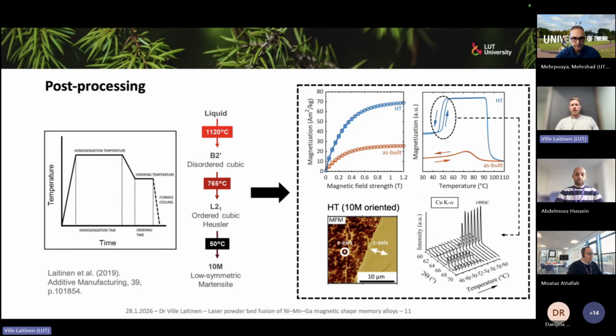At the bottom, you can see a magnetic force microscope image of a very specific orientation of a laser powder bed fusion fabricated nickel-manganese-gallium. You can see this characteristic domain structure where you have the z-axis in the plane of the image, versus when the z-axis is at a 90-degree angle compared to the plane of the image.